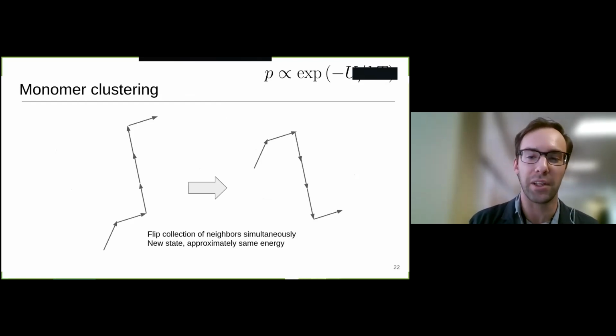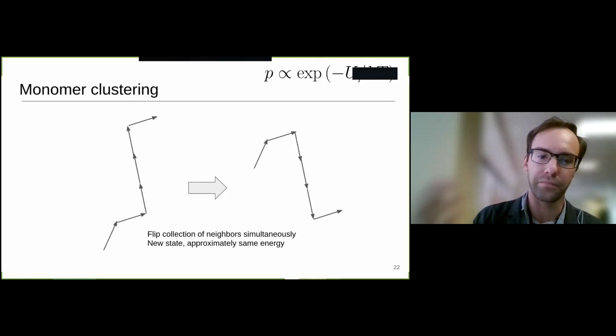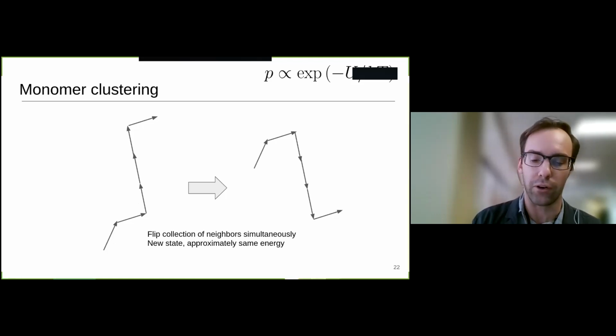And so something that has been a bit of a breakthrough with this problem recently is this idea of using clustering, which is a classical idea in Monte Carlo methods, but has not been applied to this particular problem. Because it's so difficult to flip one of two aligned monomers and not the other, we pick out a chunk of the chain in which monomers are roughly aligned with each other, and where at the boundary the monomers are roughly orthogonal to each other. And it turns out that we can make this flip without much of a change in the energy. And so this state is roughly as likely as the previous state. This ends up being a very nice way to sample things and get a sense of what the effect of interactions is within these materials.